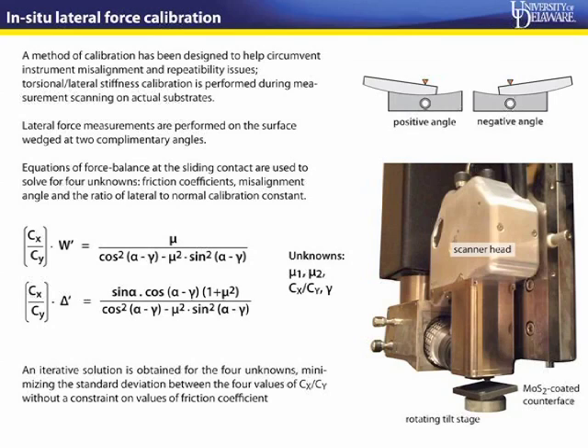So with that observation in mind, we were motivated to develop an in situ method of calibration and measurement. What we're essentially trying to do is make the calibration and the friction measurement in a single step, so we avoid the uncertainties because of the shifts in optical paths and so on.